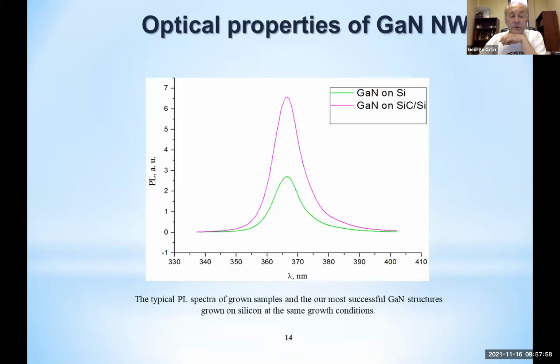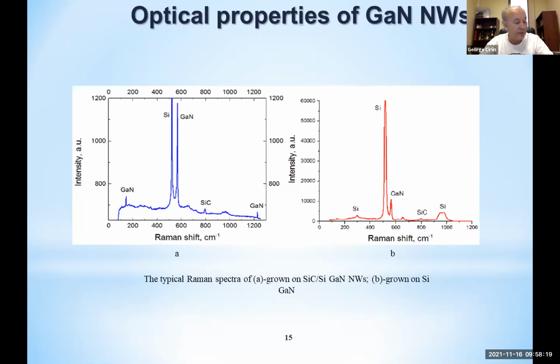And what also was interesting is that the crystallographic quality of the nanowires grown on these hybrid structures appears to be better in comparison to those grown on the silicon substrate itself. This is also in agreement, not from a photoemission point of view, but from the Raman point of view. It was proved with Raman spectroscopy that the gallium nitride nanowires have better quality in comparison to those grown directly on the silicon substrate.